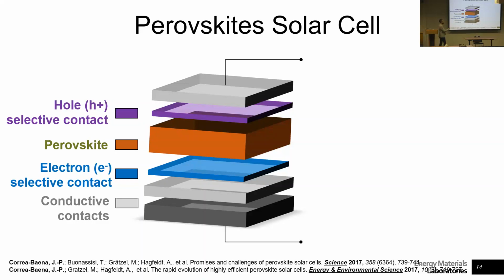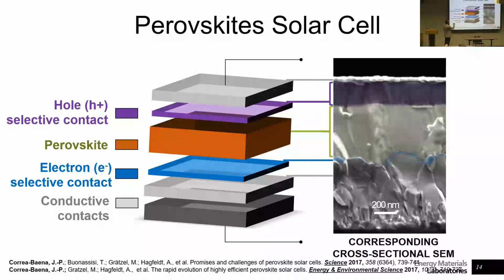We have a conductive contact, which can be fluorine doped tin oxide (FTO) or ITO, which is indium tin oxide. We have a low cost material that we put here that's going to be an electron selective contact. It's going to be an oxide like titanium dioxide, very cheap to make at very low temperatures. The perovskite is going to be a 500 nanometer layer that is also made at low temperatures of about 100 degrees Celsius, and the whole contact is also made at sub 100 degrees Celsius temperatures. And then we top it up with an electrode.